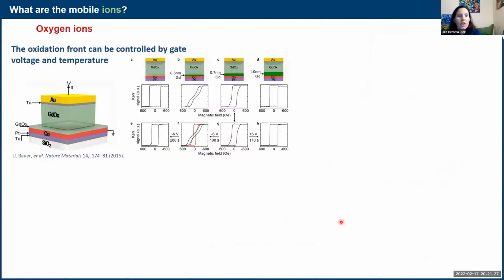Okay, so let's talk a little bit about what kind of ions we're talking about when we talk about magnetoionics. A lot of what you see in the literature today is oxygen ions. Here you can see the same graph that I've been showing you so far for solid state devices. This has been done with gadolinium oxide. And here they could really nicely observe how the oxygen could be used to modify the magnetic properties. In the top layer, you can see that they grew platinum, cobalt, gadolinium oxide, and then they also grew a thin layer of pure metallic gadolinium on top of the cobalt. And then they made it thicker and thicker, and then they just looked at the properties of those stacks.